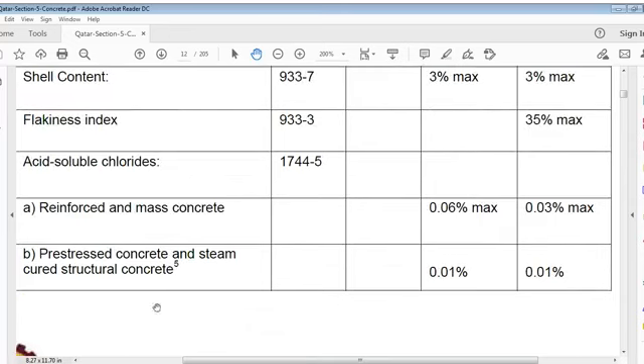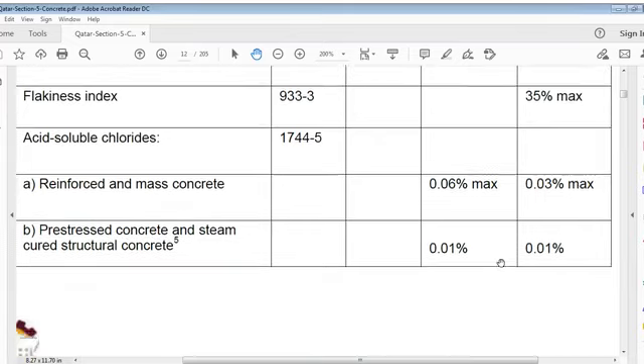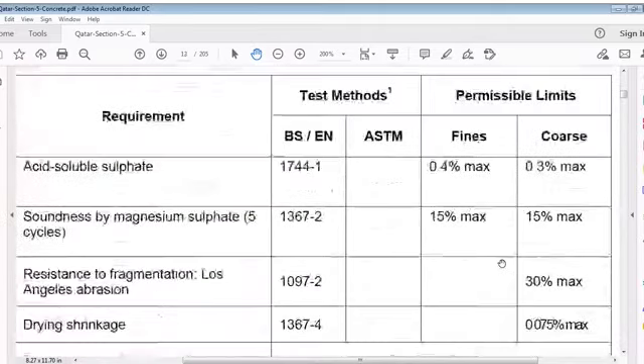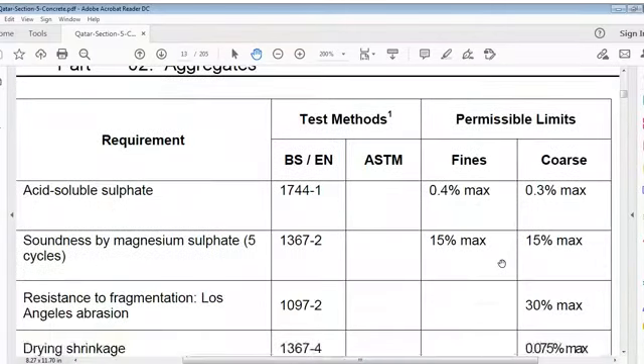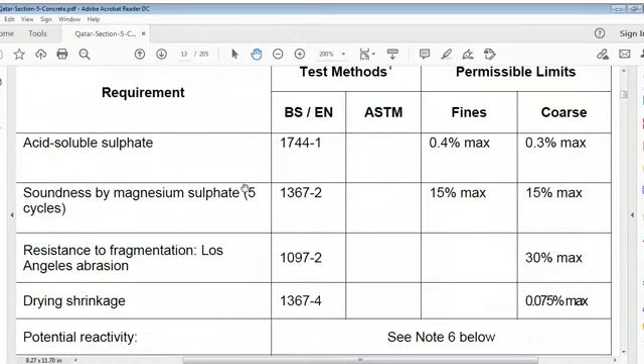Acid soluble chlorides, not applicable for plain concrete I think. Now for reinforced and mass concrete, yes, it's there: 0.06% max and 0.03% max. This is acid soluble chlorides. Pre-stressed concrete and steam cured structural concrete, kind of autoclaving: 0.01% and 0.01%.